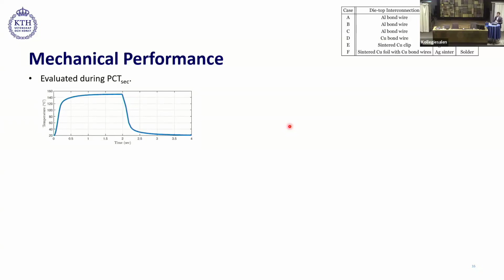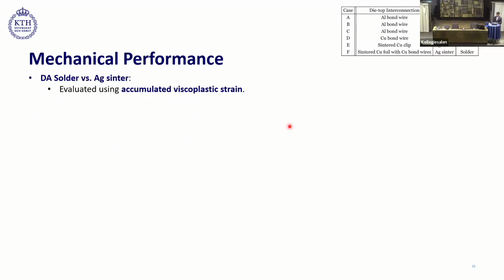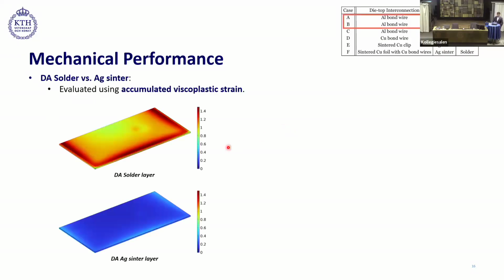Now, looking at the mechanical performance of these packages. This was evaluated using PCT-SEC power cycling. Here, the cooling time and heating time are set to 2 seconds each. First, we will look at the die attach layer, which involves solder or silver sinter. And again, we use viscoplastic strain accumulation as a performance criterion. Here, we are looking at the accumulated viscoplastic strain during one PCT-SEC cycle. And we see that the die attach solder layer exhibited higher viscoplastic strain accumulation than silver sinter.